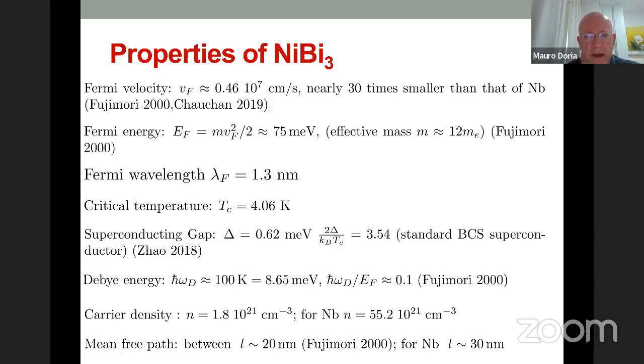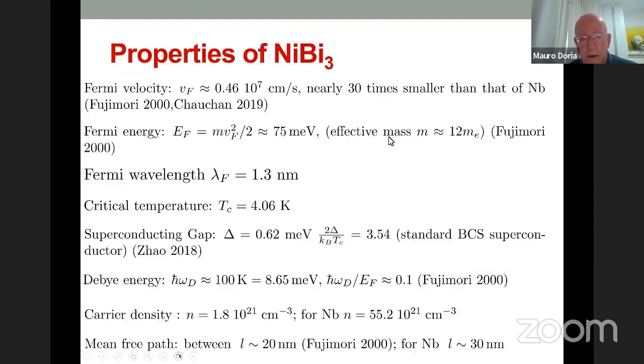He did obtain lots of information about this material, about the Fermi surface, which is much smaller than niobium, the Fermi energy, a large effective mass, according to him. Critical temperature, very well determined, the gap, the Debye frequency. In this case, the Debye frequency, the phonons, have an energy that is much smaller than the Fermi energy. So this is a BCS superconductor.